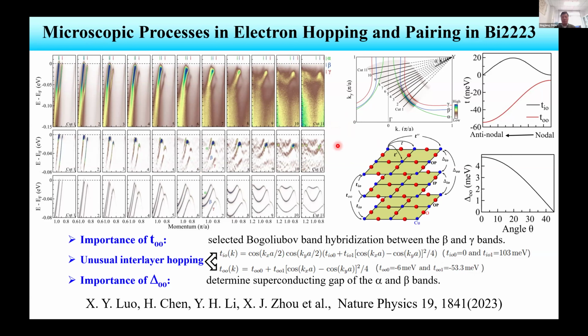From this simulation, we can see first that there's a strong interlayer hopping, particularly outer to outer, TOO. That's very important. That causes the bilayer splitting of the alpha and beta bands. The gamma band is derived from the inner CuO2 plane. The alpha and beta Fermi surfaces come from the two outer CuO2 planes. Because of the hopping between the two, there's something like bilayer splitting, which splits the alpha and beta Fermi surfaces. So we have the gamma Fermi surface from the inner plane and the alpha and beta Fermi surfaces from the outer CuO2 planes.